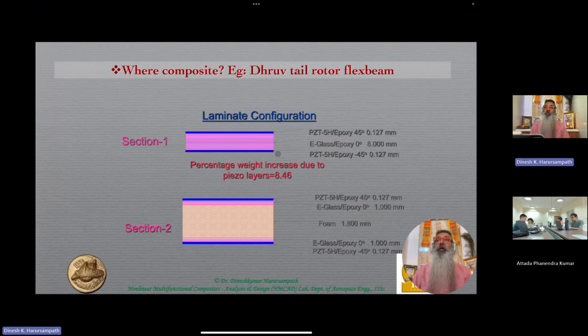And because this is in turn coupled to the twist of the blade, we can very quickly detect a delamination, and the false alarms are also very few. Because you see, when you're designing a structural health monitoring system, not only do you want to very rapidly detect damage initiation or growth, but you also want to ensure that there is no false alarm. In other words, when there is no damage, it should not issue an alarm and therefore cause delays or inefficient operation of the helicopter fleet as a whole. So that's the reason why we pay so much attention to these kinds of things.